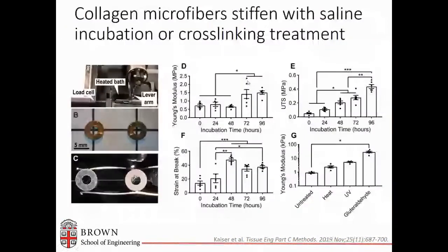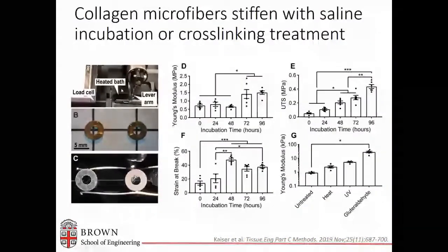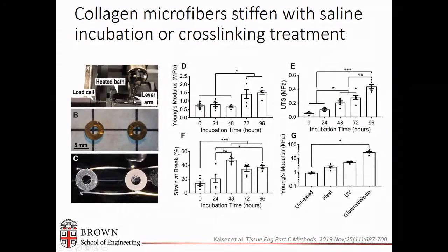We've done some mechanics on these single fibers in a heated and aqueous bath in our lab. And we've mounted these fibers between two washers and put them in our setup. And we incubated them prior to testing in a saline solution, so a salt solution, because this collagen is a full-length collagen molecule that has the end groups, and so potentially an ability to self-assemble.